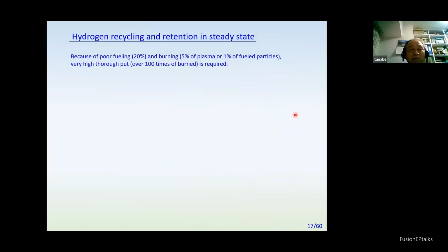Because of poor fueling, only 20% goes to the plasma, and burning is only 5% in the plasma, so only 5% burns. In total, only 1% of the fuel injected is burned. This means very high throughput is required - for 1% burn, we need 100 times the throughput of what's actually burned.